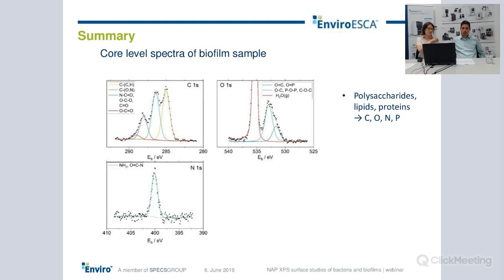So just to summarize what you just saw with peak fitted spectra. We know that the surface of the bacteria consists of polysaccharides, lipids, and proteins. In XPS, we detect that as carbon, oxygen, nitrogen, and phosphorus. But due to the chemical shifts, we can assign the peaks to some extent to these constituents. So with carbon 1s spectra, we have the aliphatic carbon from the long-chain lipids. We have carbon singly bound to oxygen and nitrogen, carbon from the amine bindings, and also carboxylic carbon. And these are also in accordance with literature from freeze-dried and frozen bacteria. So these are from acetals and carbonyls.